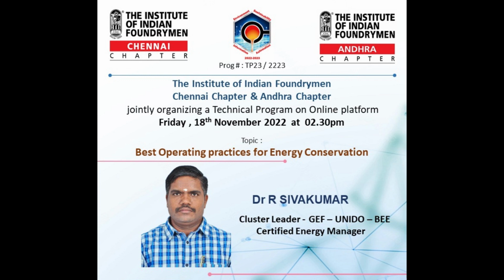But in a few industries in Coimbatore itself, one foundry was using 1.5 tons and 2 tons capacity. Because the mold is not ready, they are not able to pour the metal, so they are maintaining heel metal. Even where 3 or 4 furnaces are there, we suggested you switch off one furnace, use 3 furnaces, and take all the metal. In your case, 50, 60 kgs is not a matter, but in capacity furnaces nearly 30% of the metal is maintained as heel metal, which consumes more energy and wastes a lot of power.